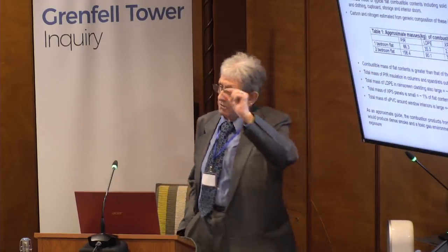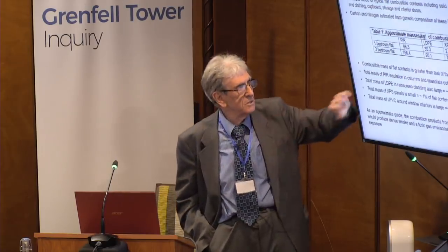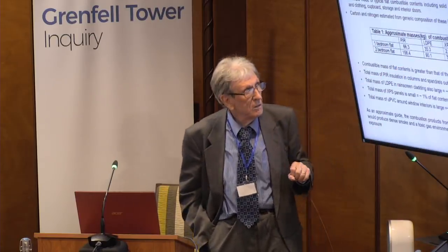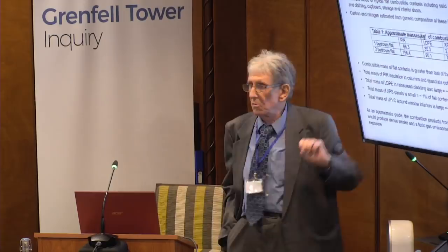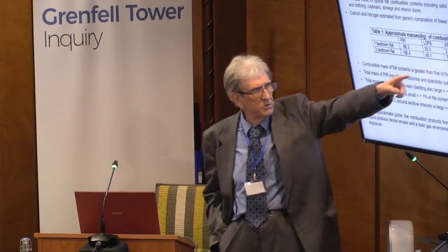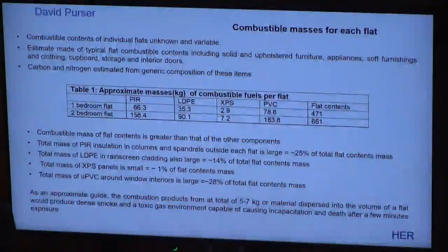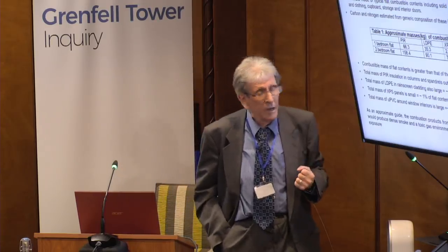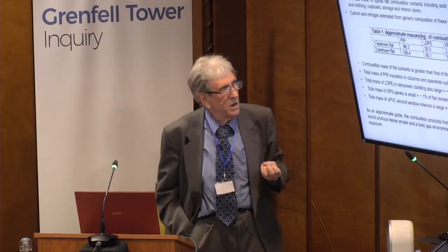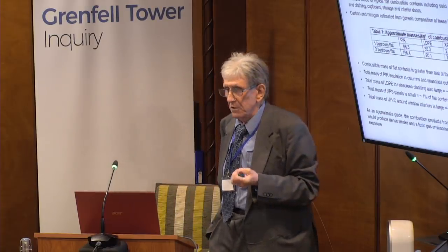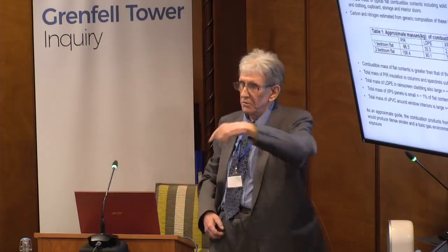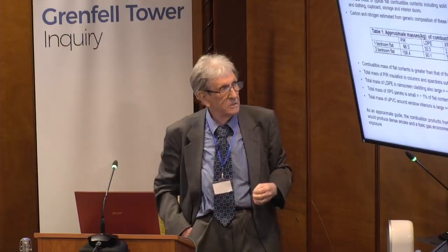The LDPE, although it's only 3 millimetres thick, is much denser than the PIR, and so actually quite a large mass of LDPE. The XPS, though, is quite a small amount, so we would expect that not to contribute too much. The PVC, and somebody's queried this, and I must admit I'm a little bit surprised, according to my calculations, and there was a lot of it there, and it's very heavy, very dense material, there's about 184 kilos of PVC in the window surrounds of all the windows of a typical two-bedroom flat in the tower.